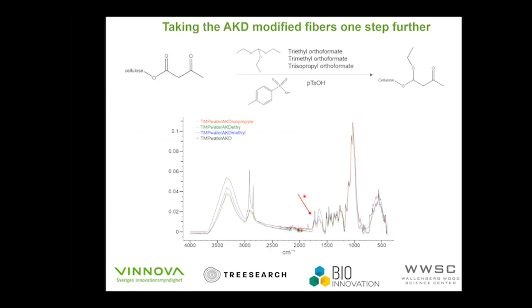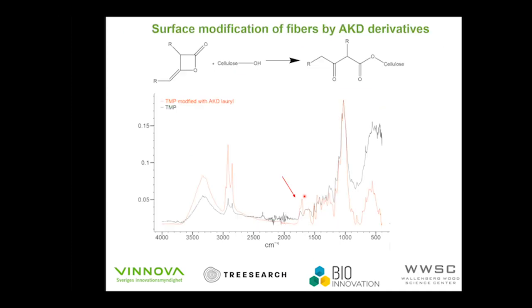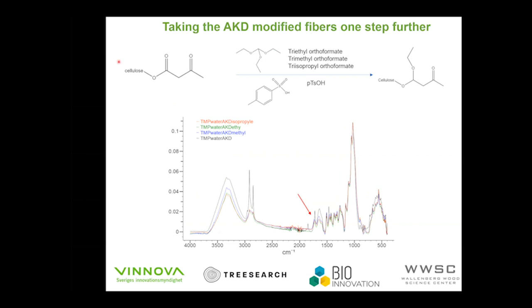Then, taking the AKD-modified fibers one step further. The reaction that I showed you has been used a lot in the industry, but what is new here? We said, okay, why not make it even more hydrophobic? We have these carbonyl groups, and we carry out another reaction where we put carbon chains on the oxygens of the carbonyl groups. We did this reaction, and again it is confirmed by IR: you can see the carbonyl groups have decreased a lot, so we can say that we have those carbon chains. So basically it makes the fibers more hydrophobic and gives better mixing in our composite.